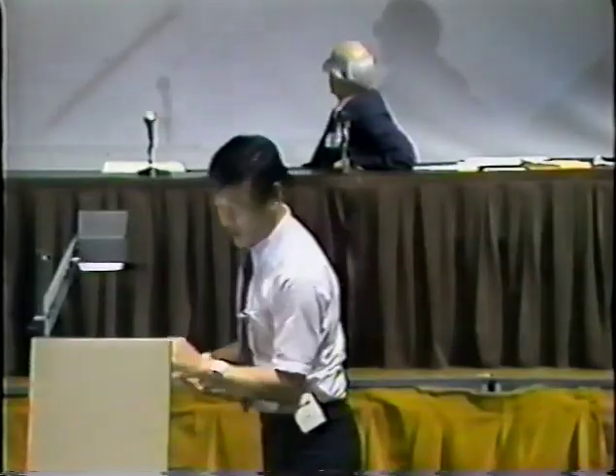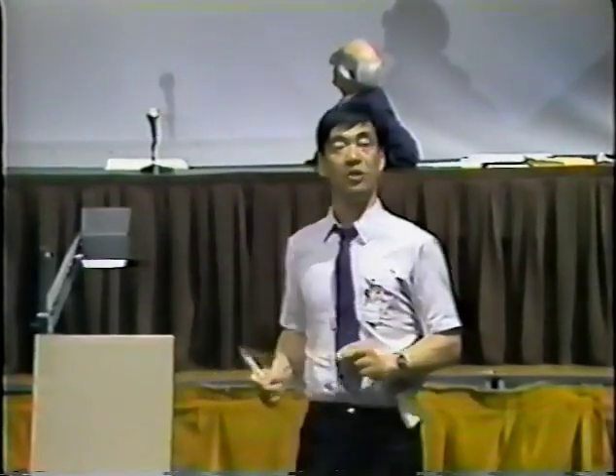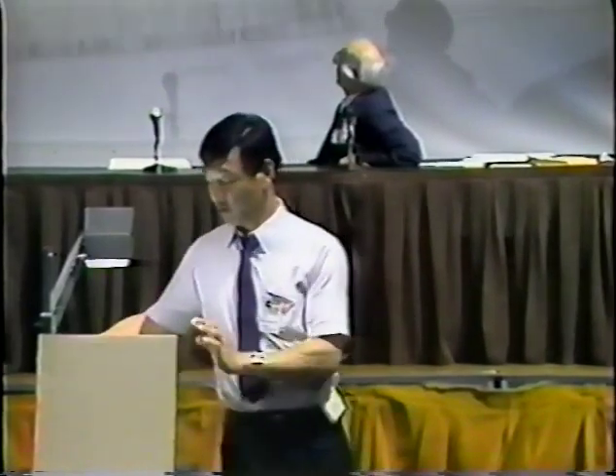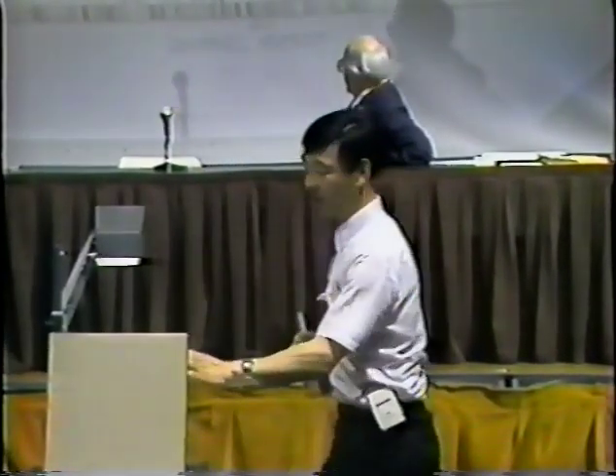What we did originally was to try to see the possibility of tritium or helium-3 or alphas. But after the electrolysis, we found very funny, curious things. This is the one without any electrolysis, so-called clean palladium. You see at the surface a lot of concentration of hydrogen. If you keep the palladium in the air, there is water or such things, so you get hydrogen on the surface at the very beginning.